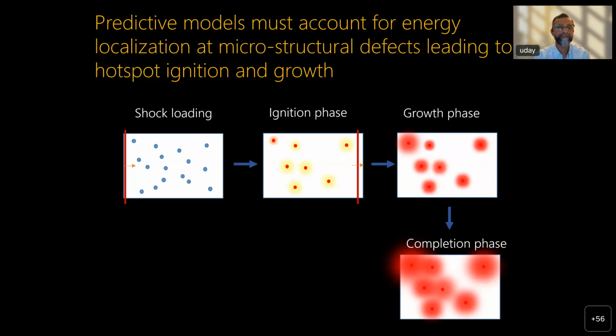Strength does matter, but it's nearly a hydrodynamic collapse. And when they collapse, there is jetting and other high-speed phenomena that happen, just like cavitation bubbles. And you form a hotspot, and the hotspots then trigger reactions, and then the reaction front propagates and fills the material, and it's off to the races at that point. And if there is a coupling between this reaction and the shock, it will then transition to a detonation, and you get what is called shock to detonation transition, and you get full blow up of the material. So that's the mechanism that we want to capture.